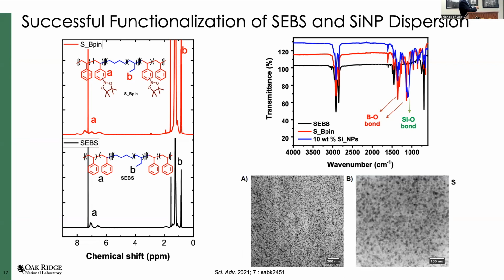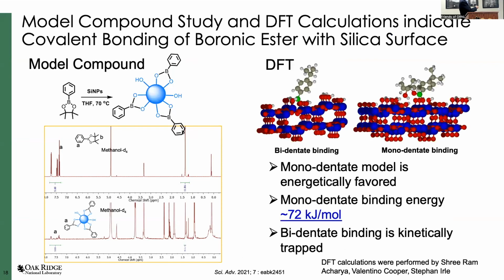But why are we saying this is chemically bridged? We have evidence. When you mix this boron ester small molecule with silicon nanoparticles, from NMR, it's shifted. Also, we did a DFT calculation. What that means is we calculated the binding interaction energies. The interaction between boron and silica hydroxyl is about 72 kilojoules. That means it's not as strong as a chemical bond, but it's much stronger than most secondary interactions. If it's hydrogen bonding, this is about 10 kilojoules. So this is much stronger than that. That's strong evidence that bonding is happening there.